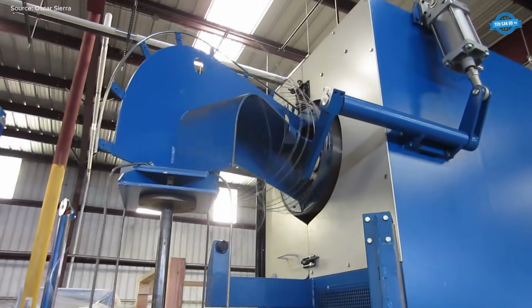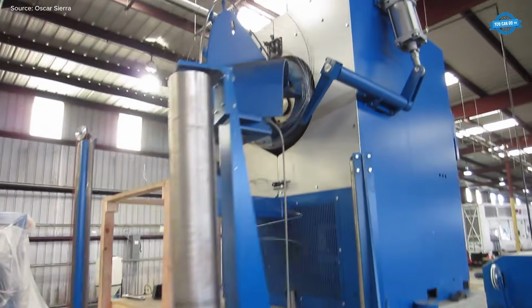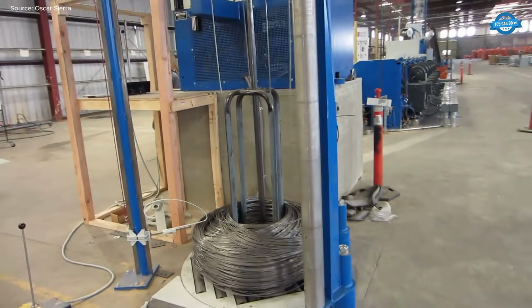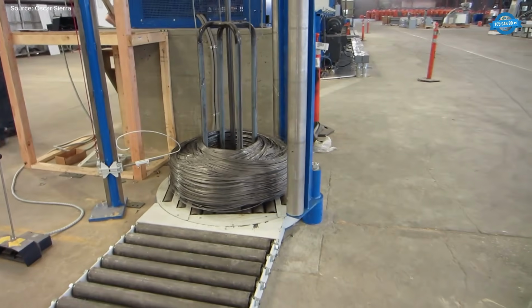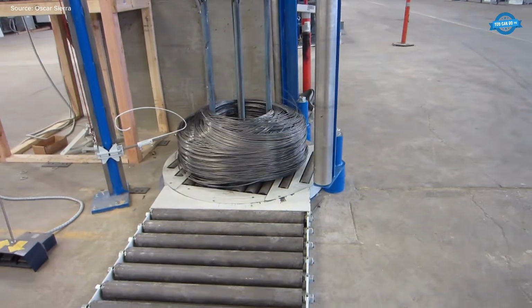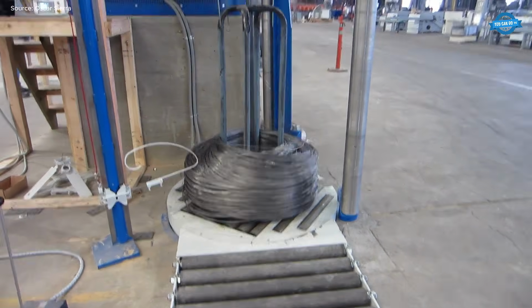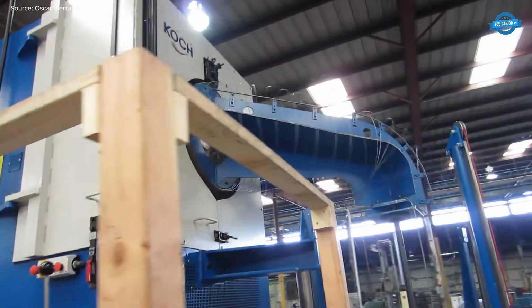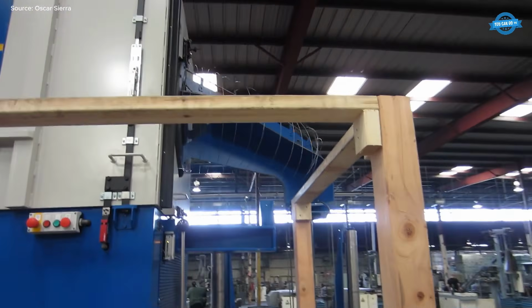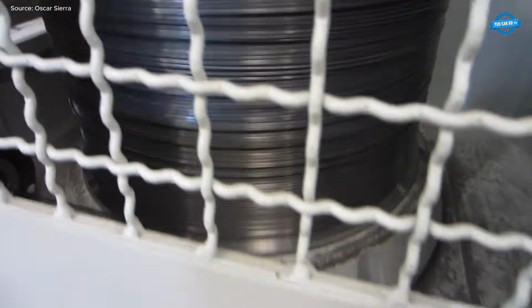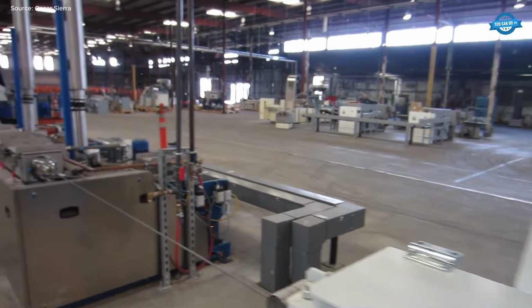With minimal investment, companies can achieve full machine speed, improve delivery times, increase product quality, and even reduce the number of active shifts. In a high-speed wire drawing process operating at 21 meters per second for low-carbon steel, achieving 1,700 tons per month requires precise technical control.